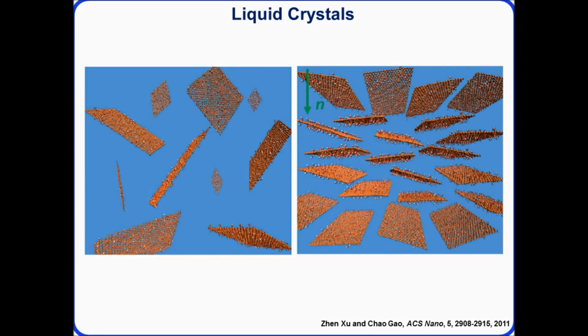Now, because of the microfluidic process, we found we could achieve very high concentrations of graphene in solution. So what happens when you confine these graphene flakes together, as you increase the concentration, they start to align and form liquid crystals. So that's hugely important because you can then control the structure of your liquid crystal, and you can make different structures from this.